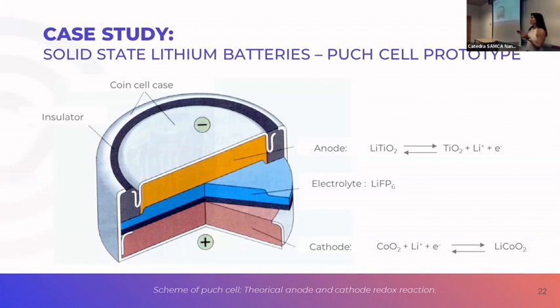Okay, we produce the ceramic filaments, LTO and LCO for anode and cathode, then print the electrodes, remove the organics to obtain a full ceramic electrode, okay, without organics. And we use a reactive electrolyte. And we study the physical and the electrochemical properties of our full ceramic electrodes compared to ceramic electrodes manufactured by casting.